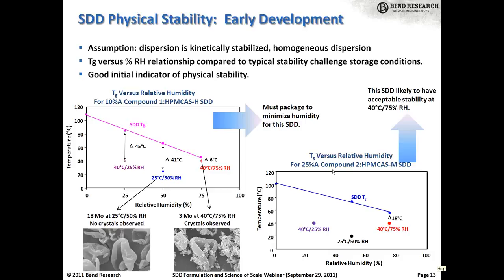In this other example, you go through the same exercise of measuring and plotting Tg versus RH. For this particular compound, which is a 25% dispersion with HPMCAS-M, there's an 18-degree separation between the 40 C/75% RH condition and the Tg at 75% RH. As such, we predict that this is likely, but not absolutely certain, to have good stability at 40 degrees and 75% humidity in an open condition.